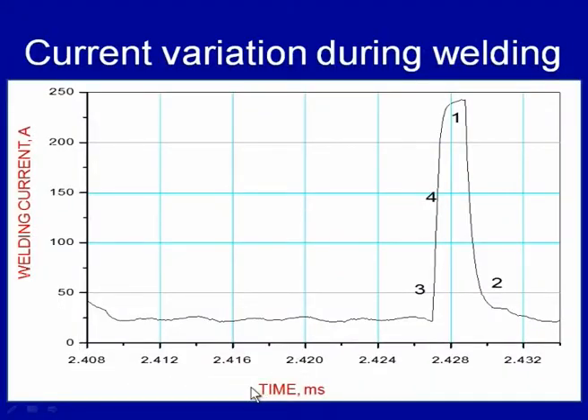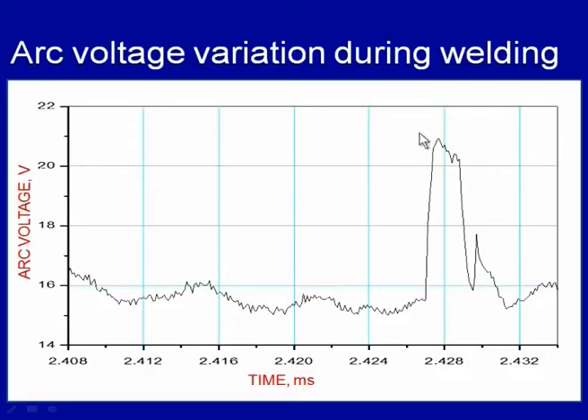If we see the typical current variation during the metal inert gas welding process, where the variation in welding current as a function of time is shown here, you can see the kind of transient conditions experienced during welding. There is a sharp change in the welding current over a very short period of time; it increases suddenly, then comes down, passing through different stages due to the fluctuation in arc length and the changing welding conditions. Similarly, here we can see how arc voltage fluctuates during welding over a very short period of time, and then it gets stabilized. However, these fluctuations keep on happening.